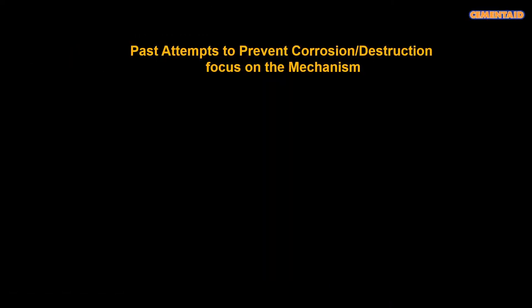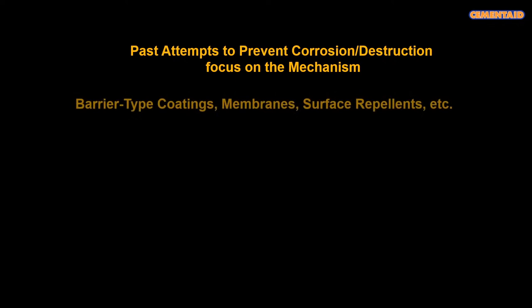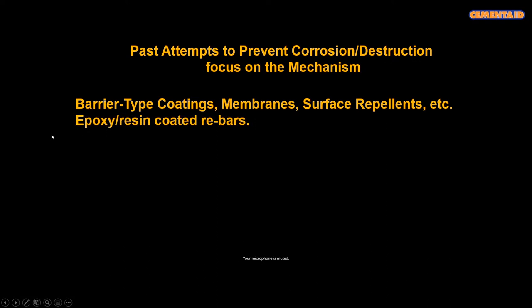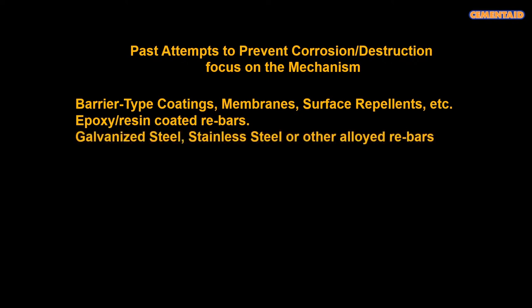So past attempts to prevent water getting into concrete and preventing any corrosion always focus on the mechanism involved. If we look at the mechanism involved, you might try using, or typically we use barrier type coatings, membranes and surface repellents. If you're worried about chloride induced corrosion, you might consider using epoxy or resin coated reinforcement, stainless steel, galvanized steel or other alloyed rebars, again to try and increase the resistance to chloride induced corrosion. Cathodic protection, another way, obviously, if you can reverse the current that's formed, you can switch off the damaging chloride-induced corrosion. But it's a very costly thing to install, and it needs a lot of monitoring.